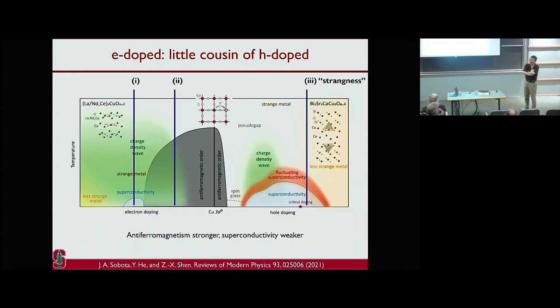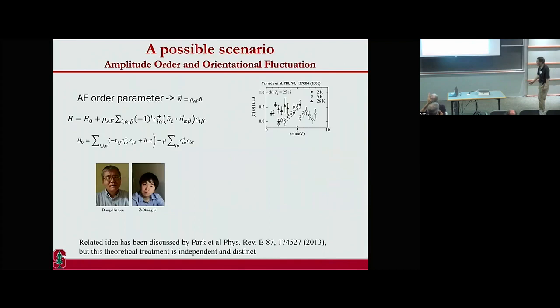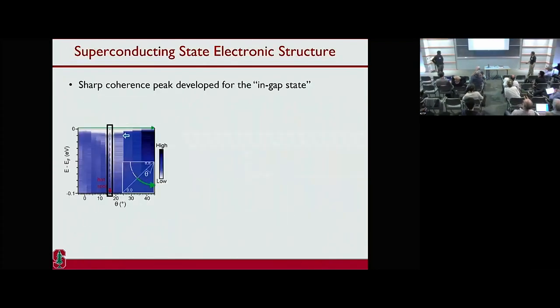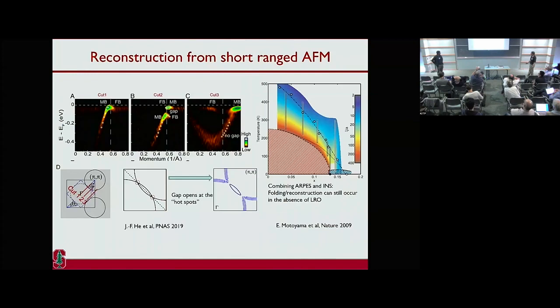Thank you. The reason I asked is that there is a quantum oscillation experiment on 0.15 doping. Not only does it show very nice quantum oscillations, moreover, some signatures of these oscillations appear to be consistent pretty much only with antiferromagnetism. We published this paper comparing this pocket quantitatively with the quantum oscillation. They are the same number. Yes, there are quantum oscillation data by Kartsovnik and company. I agree, and I believe we cited that result in this paper.